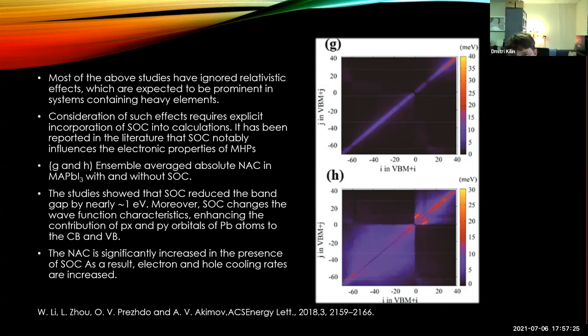Aaron, is it a correct interpretation of your result? Yeah, I would say so. And how would you interpret why in the bulk spin orbit coupling makes it quicker, if it is so? Well, they have closer density of states, so that makes it faster. And then if you compare the G and H panels, you see that the purple spreads out a lot further, including spin orbit coupling. So it basically just increases the chance of a non-radiative relaxation. So the interaction mixes a larger number of basis states. Mm-hmm. Okay, makes sense. Boston, would you agree? Yeah, it makes sense. Okay, yeah, thank you.